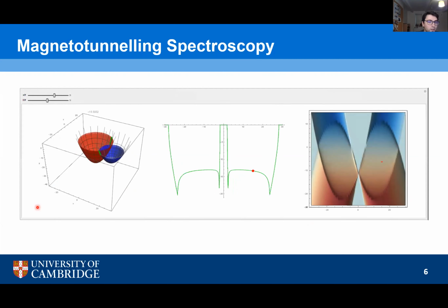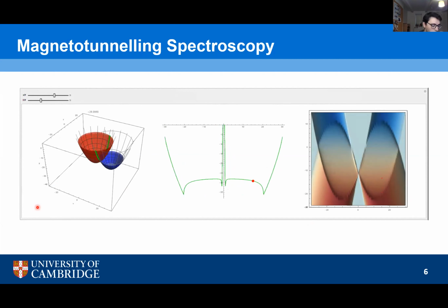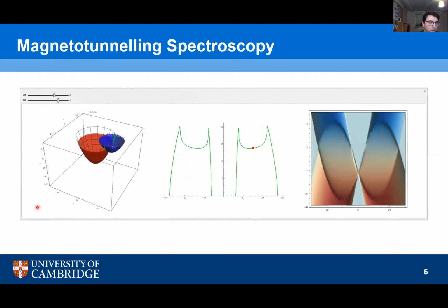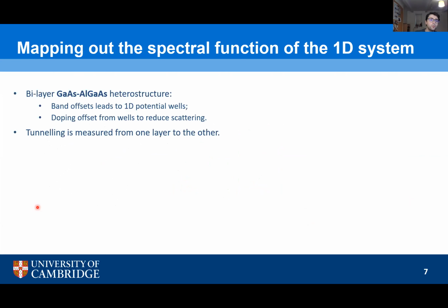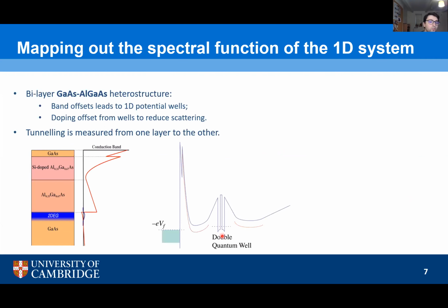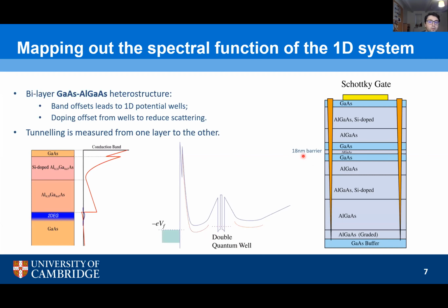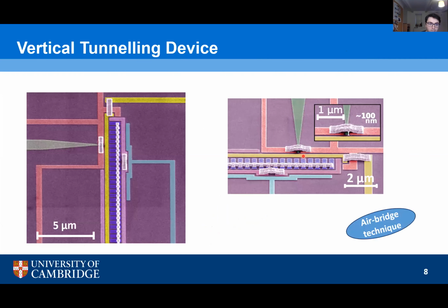Now, like I said, we're not interested in 2D-2D tunneling, we want to do 1D-2D tunneling, so the question now becomes, how do we create a 1D system? So we use a double quantum well gallium arsenide, aluminium gallium arsenide heterostructure. So essentially we have two quantum wells in close proximity. For reference, the tunneling barrier is roughly 18 nanometers thick. And these are some SEM micrographs of our device. And essentially, really the only thing I need to focus on here is this array of fingers. By laterally confining the 2D gas on the top well alone, we can squeeze this into 1D channels, and I'll show that dispersion in a moment. And then we can measure that to the bottom 2D layer, which acts as a probe, essentially.